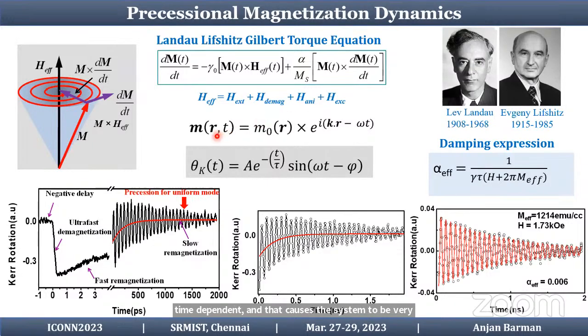And the simplest way to describe it is to propose a plane wave solution, where the magnetization can be shown by a plane wave, and under the uniform precessional condition, it can be expressed by the so-called Kittel formula. And on top of that, this is basically the precessional dynamics. We can see the precessional oscillation on top of this background. And if you remove the background, you see this time-resolved precession, or this beautiful oscillation of the spin.